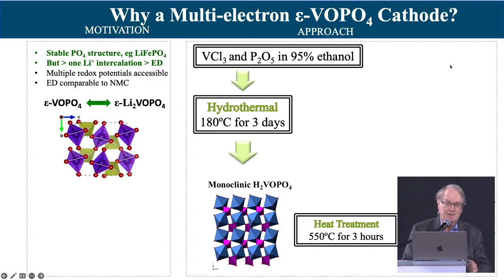As I said, what we're interested in was really, let's go to the next stage and make these phosphates as high energy density as the oxides. So we looked at this vanadium phosphate. Vanadium is very good in the sense it goes from 5+ to 4+ to 3+. So it has a nice tunnel structure, so very stable. You can make this by what we call a hydrothermal technique. You just dissolve everything in the reactor, heat it to about 180 to 200 degrees centigrade for a day or two, and you get a beautiful structure out. It's full of protons now, but if we heat that, we can drive the protons out, or we can build a battery with it and actually pump the protons out.